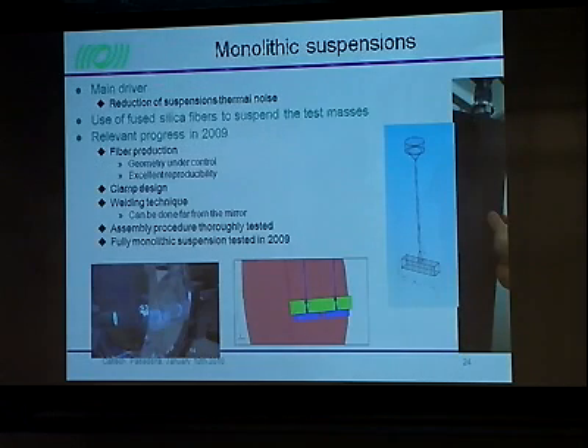The other important piece of Advanced Virgo is the suspension. There the goal is to reduce the suspension thermal noise, and so to use fused silica fibers to suspend the test masses, fused silica fibers which are monolithically bonded to the mirrors. There was relevant progress made in 2009 in this field. People are now able to produce fibers controlling the geometry precisely. They reach very good reproducibility, and they realized a system to attach the fiber to the mirror such that if for some reason the fiber breaks, you can actually dismount the system, weld a new fiber, and remount the system. And it was tested, because the fiber actually broke when the first full monolithic suspension was tested last year, and in a few days we were able to recover, replacing the broken fiber with a new one.